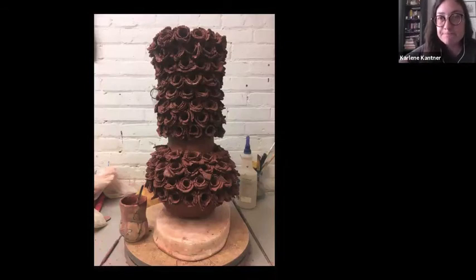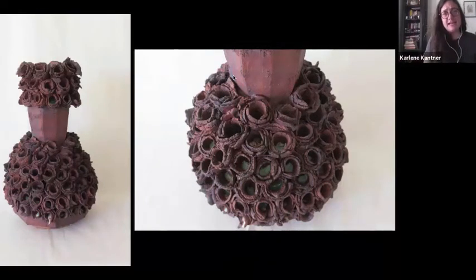It's just waiting. Karlene, was there green in the other one before? It's ozone blue actually. Okay. So I just stained. You can see where it's really rustic and metallic. It's an oxide stain, so it can absorb, sort of like watercolor would absorb into paper. The stain absorbs into the clay body and just embellishes the contrast and the texture, especially where the sand lands, without covering it. But I did want to do little pops of detail. So in each one of these, throughout the whole thing, there's a little dollop of Cone 6 ozone blue glaze.